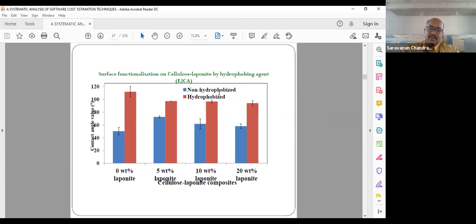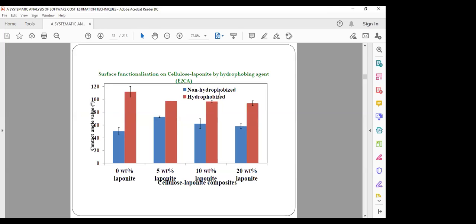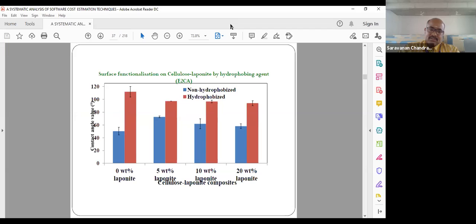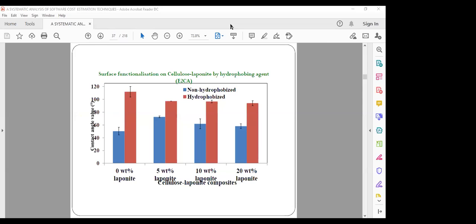So that is why we treated it with different hydrophobic agents. If the contact angle value is less than 90, it is hydrophilic. Above 90, the contact angle values are reaching 120 degrees. So next slide.